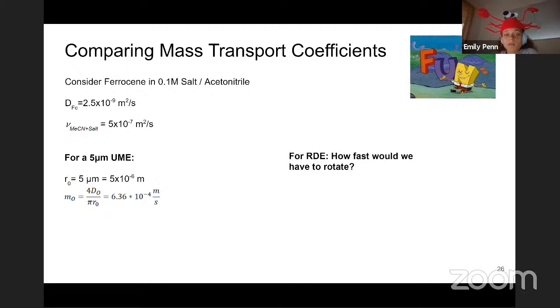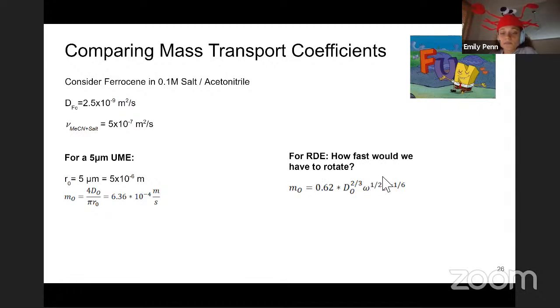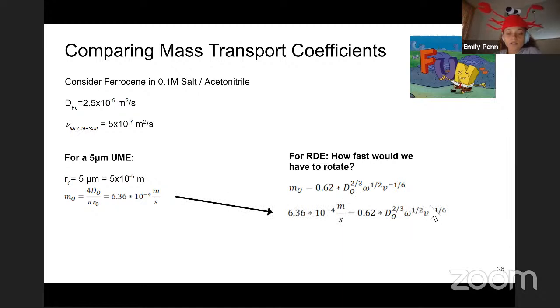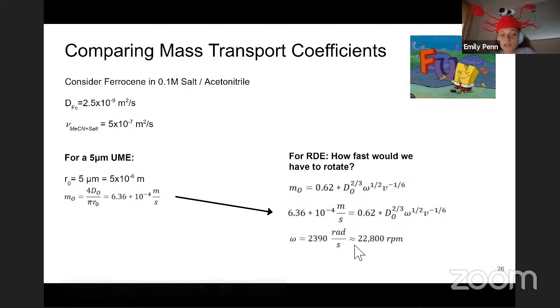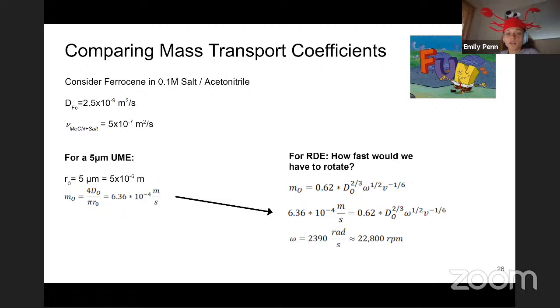If we wanted to have the same mass transport coefficient at an RDE, it could be interesting to know how fast we would have to rotate to have that same mass transport coefficient. So from the previous slide, we know that the mass transport coefficient at an RDE is related to the kinematic viscosity, the rotation rate, and the diffusion constant. So using the values that we have for the system, and then setting it equal to the mass transport coefficient for the ultramicroelectrode, we can then solve for the rotation rate that would give us an equal mass transport coefficient. Interestingly, it's super high. So to achieve the same mass transport coefficient, you would need a rotation rate of almost 23,000 RPM. That's considerably higher than the normal rotation rates that people use for RDE experiments.